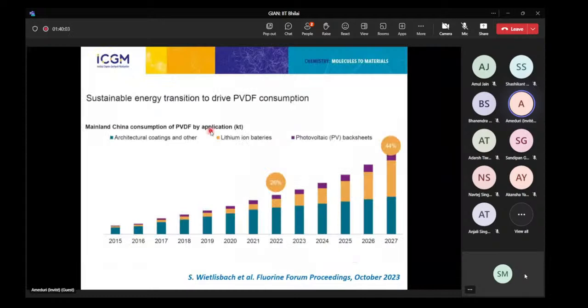So the sustainable energy transition is driven by PVDF because gigafactories of lithium-ion batteries are being built, and we have 4 gigafactories in France. There are several hundreds in China. I think there are also gigafactories in India. And again, the estimation for PVDF in lithium-ion batteries is increasing a lot, compared to that of photovoltaic, which is slightly increasing. And for architectural systems, it's a little bit steady with a very slow increase. So for the batteries, from 20 to 44, almost double in 5 years.